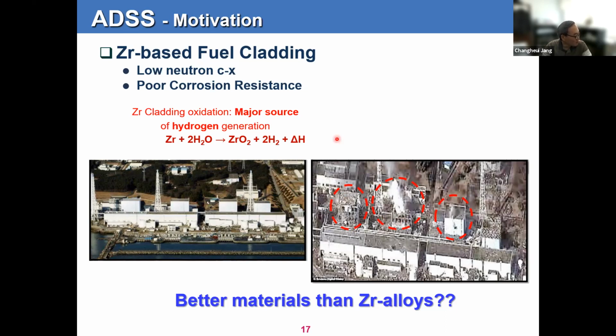So one of the reasons why the Fukushima accident became more damaging was the explosion, and that explosion was caused by hydrogen. That hydrogen actually came from the corrosion of zirconium. That zirconium is used as a fuel cladding material of water reactors. And zirconium is known to have a very aggressive corrosion reaction at relatively high temperatures, somewhere around 900 to 1000 degrees. It produces a huge amount of hydrogen, and unfortunately, this is an exothermic reaction. So this is actually a self-accelerating reaction.